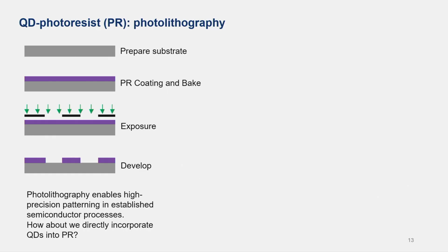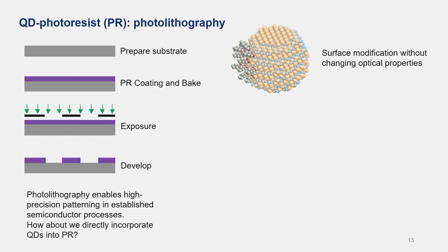Photolithography is very well developed in semiconductor processing at this point. And what if we can make the quantum dots compatible with the whole process, basically making a quantum dot photoresist that can do all the lithography that's well developed at this point? Again, I want to emphasize the uniqueness of this material: the surface and the core material are kind of separated. You can modify the surface so that it's compatible with the photoresist that you need, and then you can do the whole process just like normal photolithography.